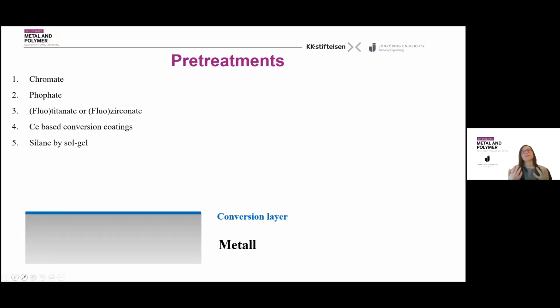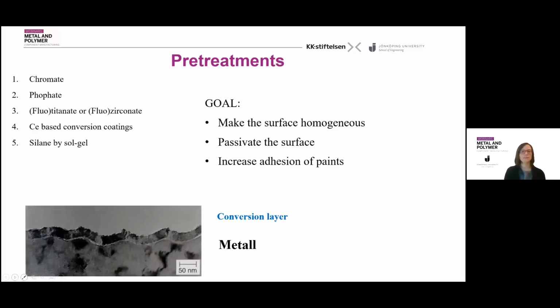Because adhesion is so important and because surface preparation is so important, we don't stop at cleaning the surface. We usually add something called pre-treatments. We want to transform the surface of the material with the goal to make it more homogeneous, to hinder the problem given by elements like iron, copper, and silicon. In some cases, to passivate the surface to increase corrosion resistance of the material, but very often to increase adhesion of the additional layer, especially if we work with paints that are of such a different chemical nature.